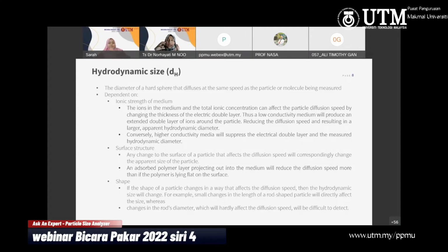So if you have nanoparticles and you want it to have something coated with another polymer, this might give you a different result. All right, because for DLS they measure not the solid of the particle itself, but including the layer outside of the particles. So that's why sometimes you can see that the size is bigger compared with the transmission electron microscope result. So that's why your result is bigger compared with TEM results. Okay, because it measures the total of the particles, including the layer.